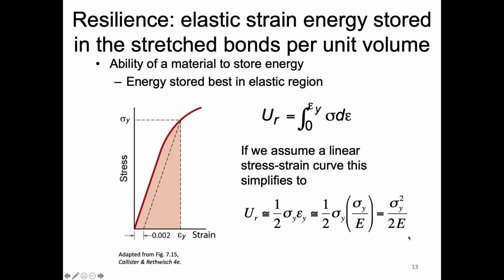So all this down here is just approximating this integral to a very simple relationship of the yield strength squared divided by the elastic modulus, E. Here this is from a different reference, so I term the elastic modulus E again, but keep in mind our book is going to be a little different. More or less, we're taking this area underneath the curve as a triangle, using the elastic modulus, the yield strength, and the one half to look at the triangle here.